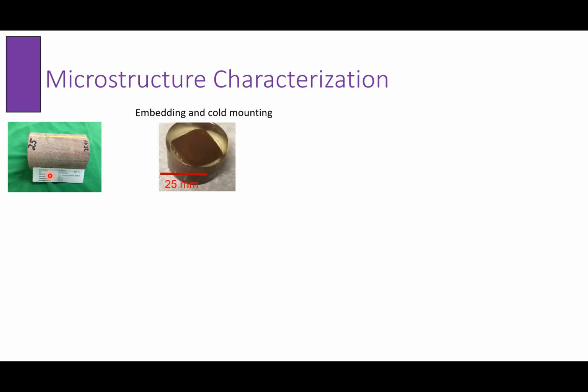So for the microstructural characterization, very similar to what was pointed out before, a lot of the time those experiments are going to be highly dependent on the way the sample is prepared. So literally we spent months just figuring out how to prepare the sample, because if you don't have the right sample preparation procedure, you're going to have erroneous results. So this is our process.